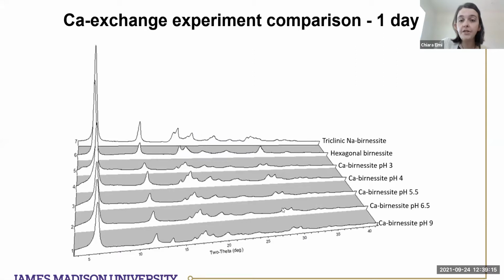With the cation exchange, I did different pH of this solution, and I noticed that changing the pH, the calcium Birnessite structure changes from a triclinic to hexagonal. So it's a structure that is between a triclinic and a hexagonal, but definitely closer to the hexagonal Birnessite. So we notice that the exchange is not affected by the cation in the interlayer, but is affected by the pH of the solution.